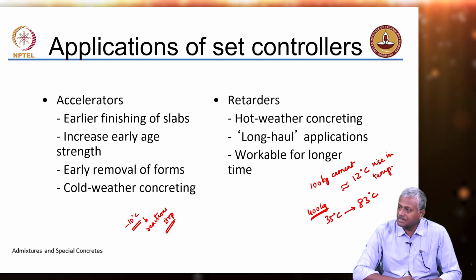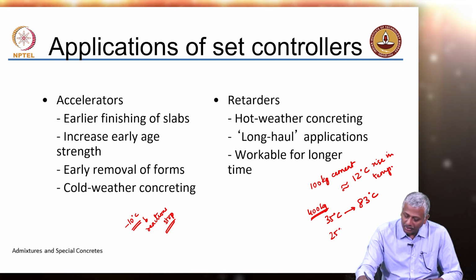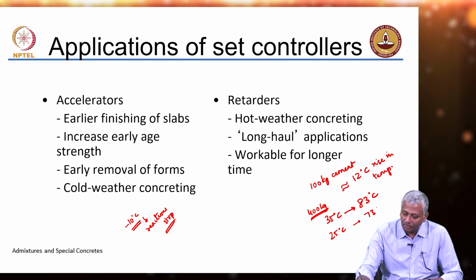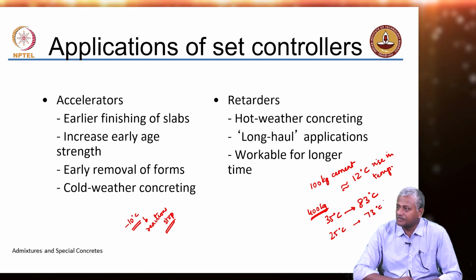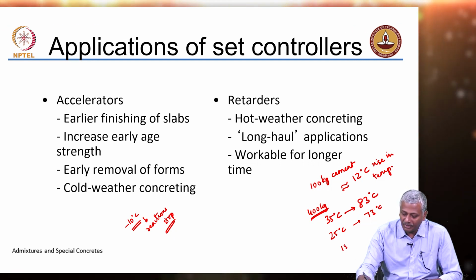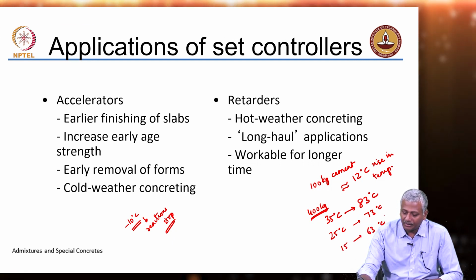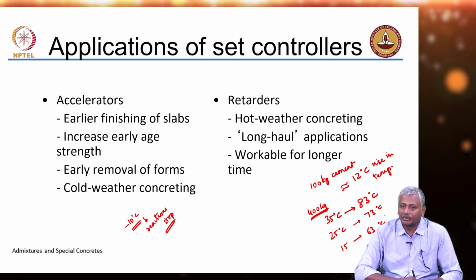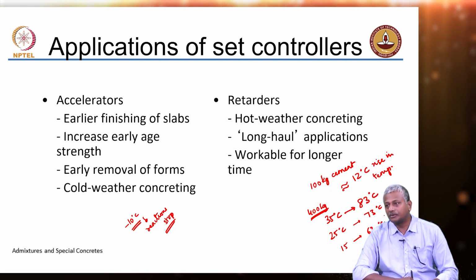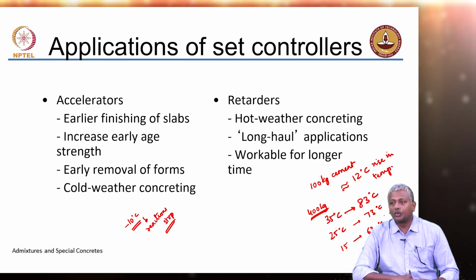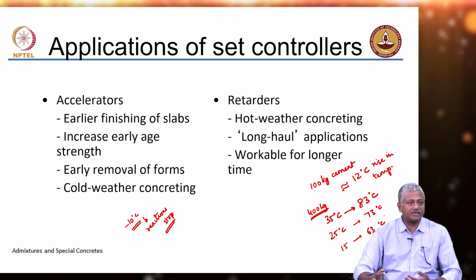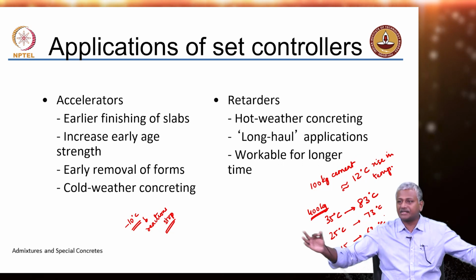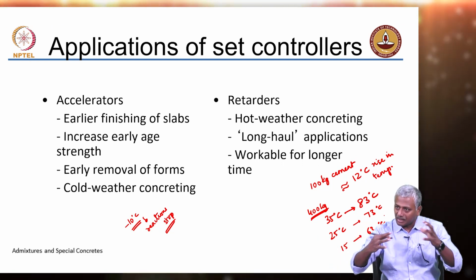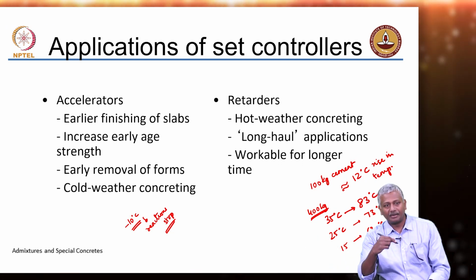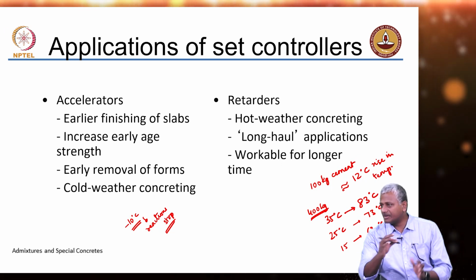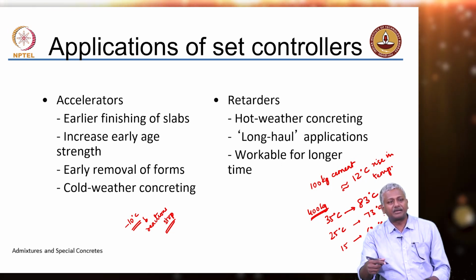So, same thing in the same job site, you try to lower it to 25 degrees Celsius, you are automatically cutting down the temperature rise by 10 degrees. If you go down to 15, you are further cutting down the temperature of the core. It is beneficial therefore, to place your concrete at low temperatures. This is in case of mass concrete structures where we expect that the size is too large and the concrete will start heating up significantly in the center. For normal beams and columns where size is not so big, we are not that concerned.